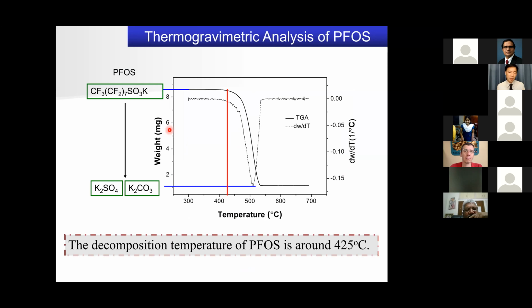But in order to look at a thermal treatment process for PFOS, for example, we have to look at whether it will evaporate too early. If it evaporates too early, if the generation of the perfluorocarbons happens at too low a temperature, we don't have a chance to really capture it, or at least sufficiently react with it. So we find out, well, usually you probably will have the temperature go up to 425 degrees Celsius in order to get these perfluorocarbons to escape from the system.